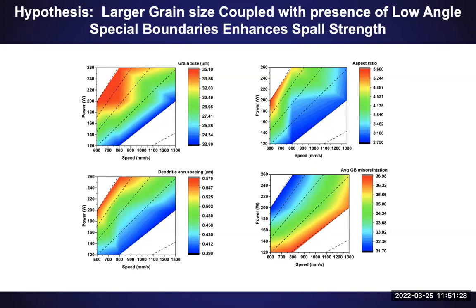I think we do. I guess there's two answers to that. We do understand that grain boundaries or other defects in the material, we call them weak links, act as sites where voids tend to nucleate. So we understand where and when, for the most part, voids nucleate. Now, the second part of that is, can we model that accurately, for example, in our continuum models? And the answer to that part is not quite, because there are some models out there that try to connect void nucleation with microstructure, but I think they're still in their developmental stages.